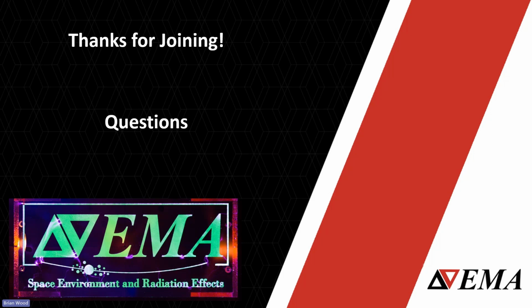Another big one that we're doing in conjunction with the main test chamber is trying to provide higher energy electrons as part of our irradiation suite. As I mentioned, we can go up to 100 keV. We've got dual sources, which is really good to more closely mimic the space environment, but we were lacking in the higher energy portion. So we are developing and having a strontium-90 source built for us. Essentially, it's an array of strontium-90 pellets in a custom housing with a gate valve shutter, and that would be integrated into our load lock chamber. Like I showed, where that UV source was, we would just bolt on our strontium-90 array.